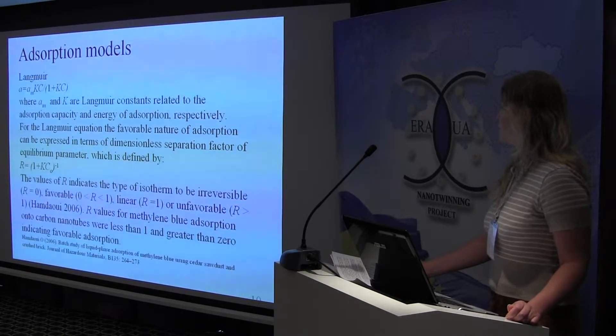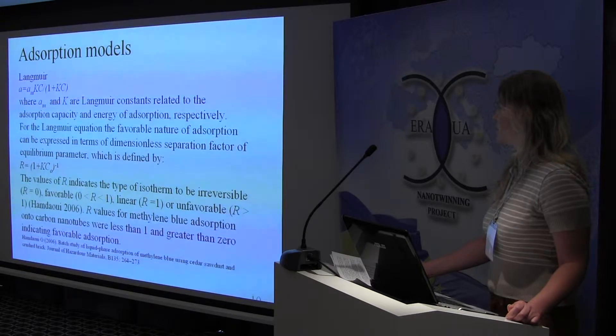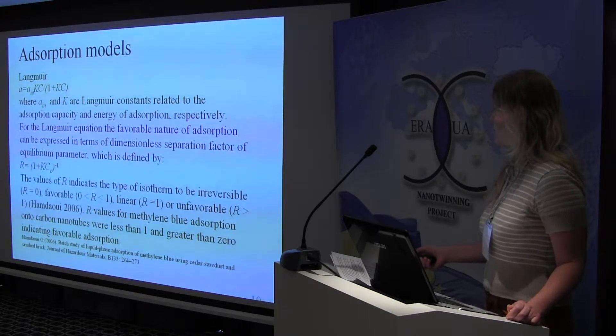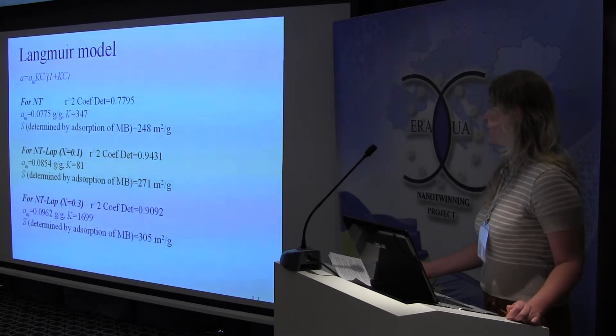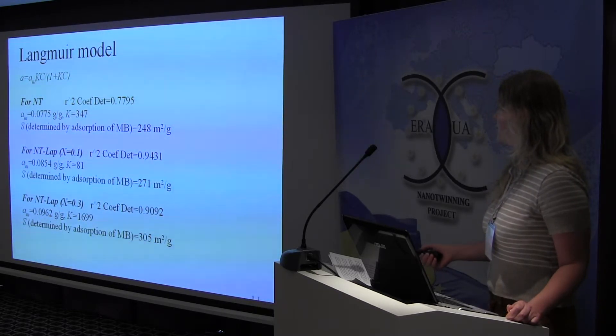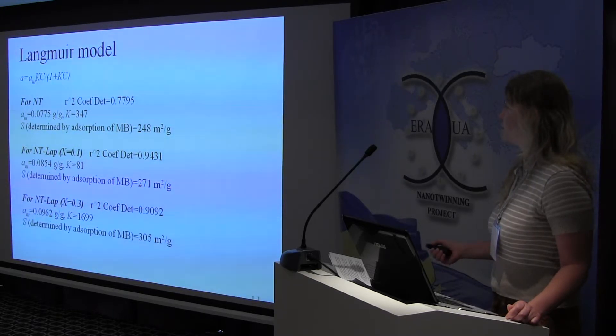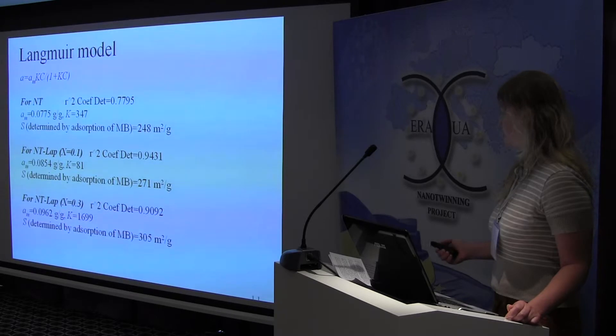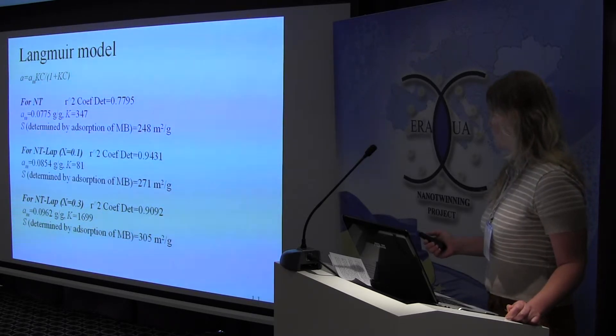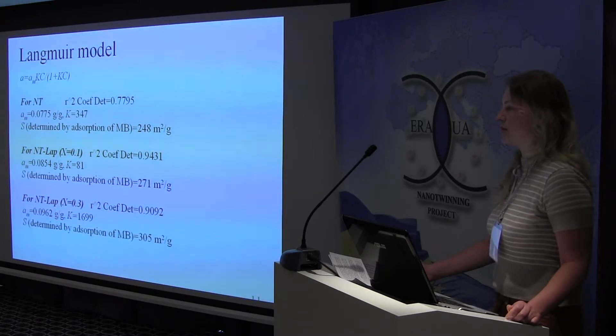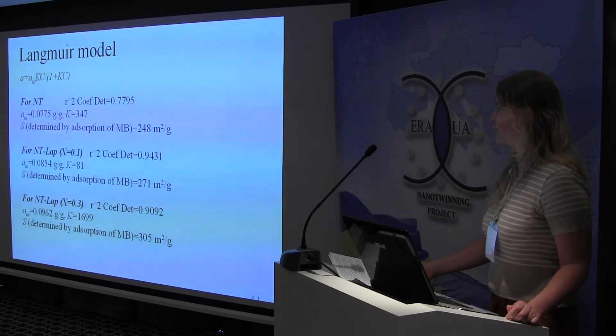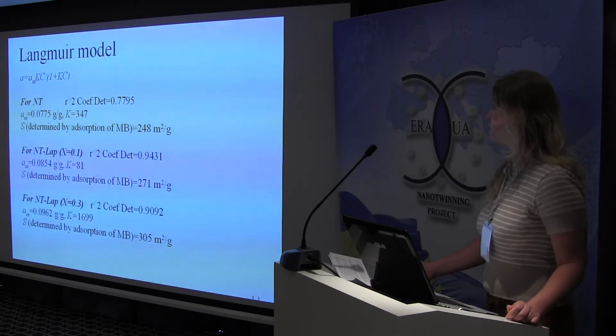For the Langmuir equation, the favorable nature of adsorption can be expressed in terms of the dimensionless separation factor, defined by the shown formula. We calculated the monolayer adsorption capacity of each adsorbent and determined the specific adsorption area by adsorption of methylene blue. It was shown that decoration of carbon nanotube surfaces by laponite leads to an increase in the specific surface area by 1.24 times.